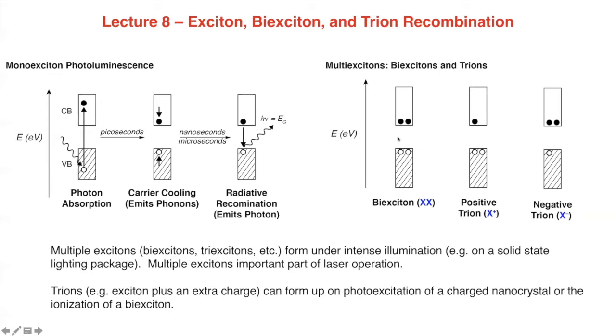Okay, so that's familiar. In quantum dots, actually, it's pretty common to also form other kinds of excitons, including biexcitons. So a biexciton is just a pair of electron hole pairs. So 4 excited charges. And this happens all the time. It's not that hard to excite a quantum dot twice before it emits. People study what happens if you excite it 3 times or 4 times or 5 times or more. And those kinds of photophysics are fun, and very important to applications like lasers, for example.